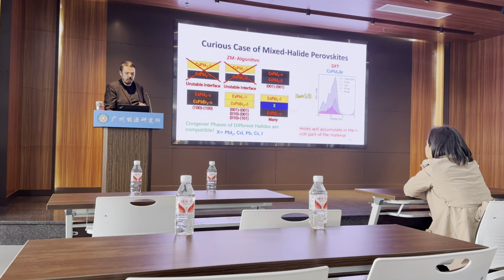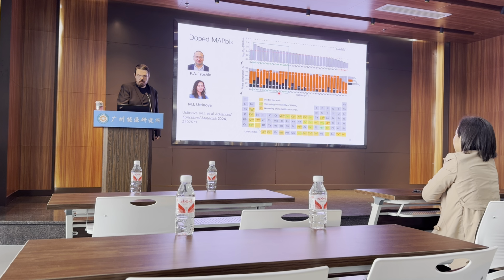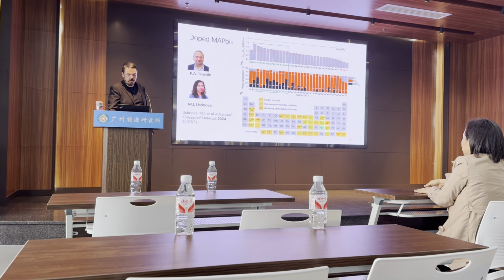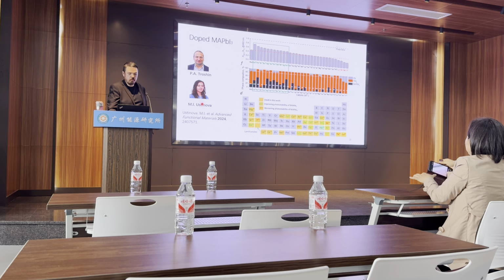So when we have yellow and black phase, there has to be something in between. Basically there's a sandwich and there's something in between the sandwich. So possibly it's cesium iodide, for example, or there's other phases of cesium iodide, like CsI3 if it's iodine rich. So here was a really impressive work by Pavel's student, now postdoc in Italy, Marina.